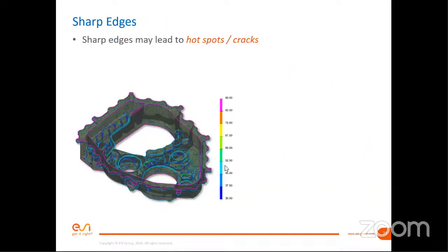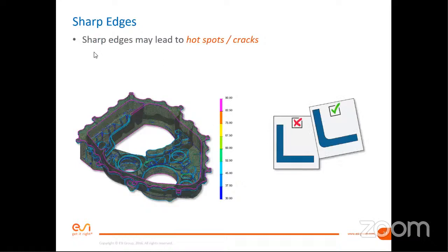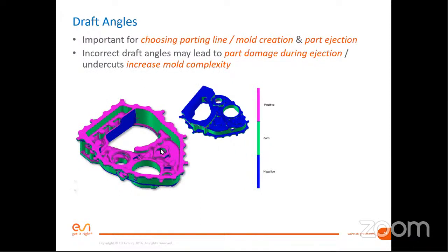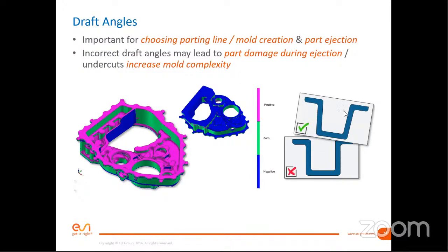That's obvious. Then we can, of course, also do the sharp edges analysis. Again, a sharp edge is not good from the castability point of view. The goal here would be to create the design as smooth as possible without sharp corners. And from the molding point of view, with this tool, we are able to validate if the casting or part draft angles are in correlation with how the mold could be prepared. You can see, of course, if you have such a shape without any angles, you are not able to produce it, because you are not able to take it out of the mold. So the goal here would be to do it like this.